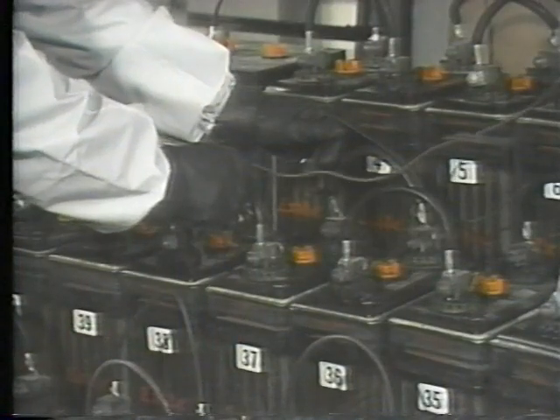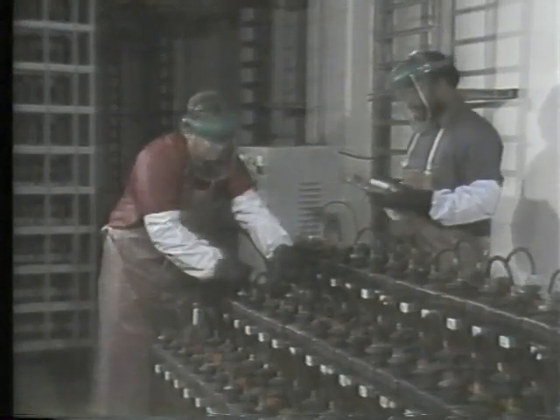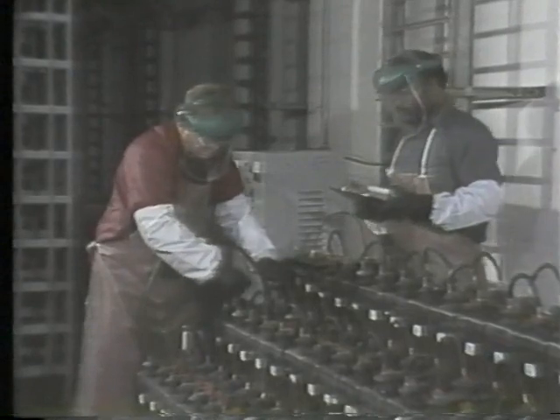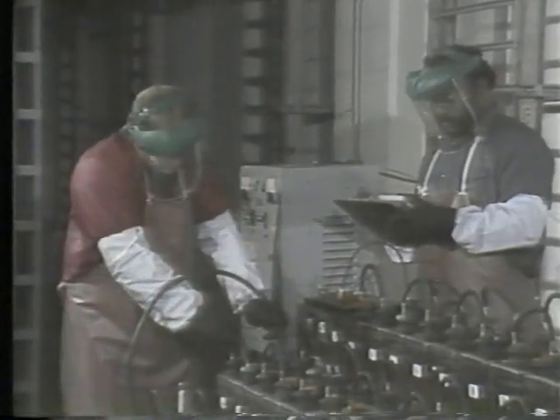The cell could be sulfated. It could have been contaminated somehow during watering, or it may have separator damage, which can be caused by excessive heat. Whatever the reason, cell number 34 will no longer take a full charge, as we've proven in this section by testing its specific gravity, giving it an equalizing charge, and making cell voltage measurements. After voltage testing has been completed for all 58 cells, we'll come back to see the next step in maintaining a station battery when we take a look at cell replacement.